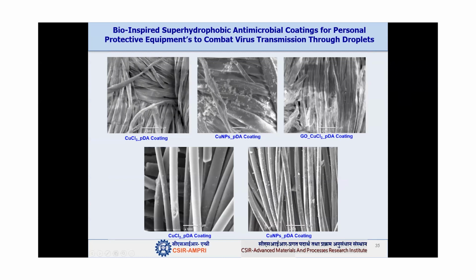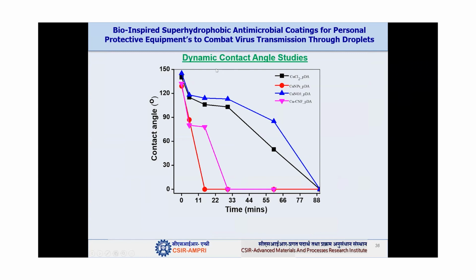So the coating is there. We have tested it by SEM micrography, and these are the dynamic contact angle results, which show that, particularly for copper nitrate and for copper chloride, even after 60 minutes we still have more than a 60 degree contact angle intact on the fabric.